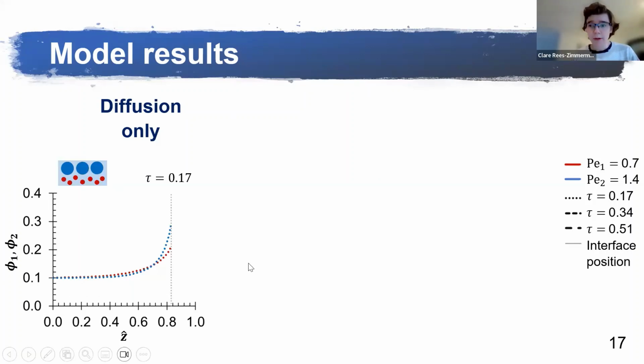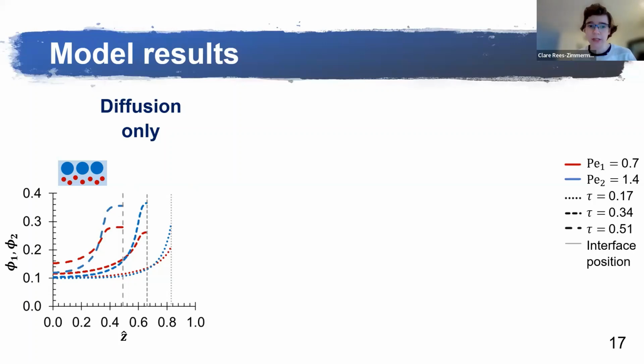Then I show you what the profiles look like at a later time. You see that the solvent interface has receded inwards due to evaporation. At the top surface, the right-hand side of the graph, we see that the film becomes more concentrated. And we see that at the top surface, the blue line is above the red line, which is showing a prediction of large-on-top stratification, which is what we'd expect from a diffusion-only model. Further down the film, the profile's still pretty flat because it's not yet affected by what's going on at the top surface. I've added on a few more lines here for later times, and we can see this large-on-top stratification developing.